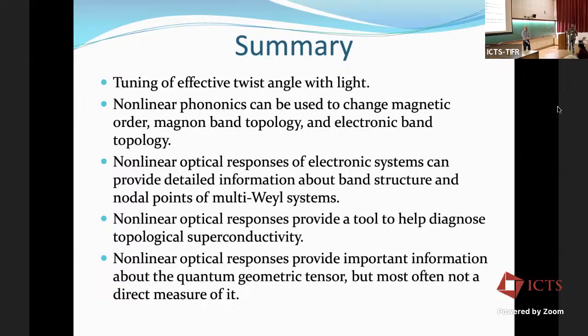So that's a good question. What sets the time scale for which you have this transient crystal structure change? Is it the pulse time that it's spending in the material or something else? It's the phonon lifetime of the IR mode. So as long as that IR mode remains excited, and it's going to decay, but basically that's going to set the time scale. Because as long as that IR mode is oscillating, whatever its lifetime may be, then you're going to have that transient structure change.